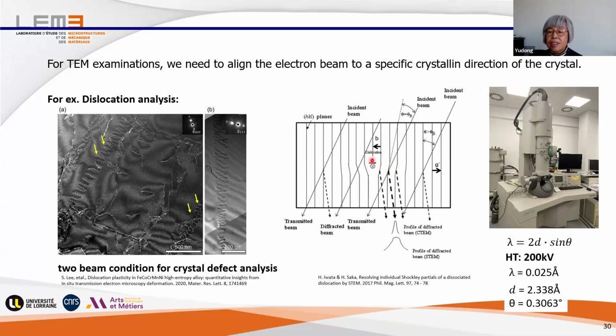With the existence of the dislocation, this plane is distorted in this area. If we can make only this small part of the plane in Bragg condition, we will have very nice, you see, fine lines of dislocation. And only this plane in Bragg condition, in TEM, we call it the two-beam condition. And if only this part is in Bragg condition, we call it the weak beam condition.